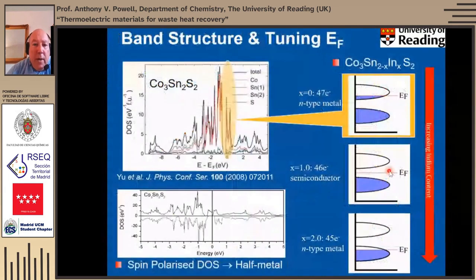And what that means is we have a highly structured density of states, as we can see here. These are some band structure calculations from the literature. Our collaborators at Reading have also done some spin polarized calculations, which confirm that it is a half metal. But the important point is in the region of the Fermi level, we have two bands, the upper of which is partially filled in the stoichiometric end member. So what we've been looking at is can we lower that Fermi level through this region of a highly structured density of states and increase the Seebeck coefficient and improve the thermoelectric properties.